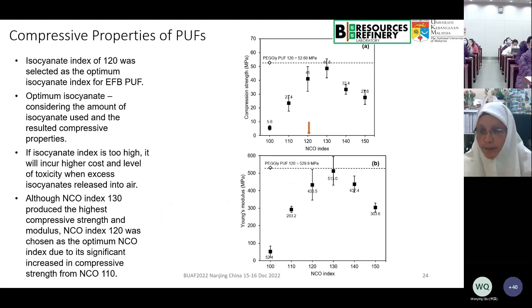So what we did is we make polyurethane from that system, and we managed to get polyurethane foam using water just as a blowing agent, because of isocyanate. When it is attacked with water, it releases lots of carbon dioxide, and that carbon dioxide will be used and become foam. So you will notice that as you increase the isocyanate index, the compression strength of the polyurethane foam increases, and later decreases. So we select 120 because we don't want excess isocyanate in the system, because it is not good.